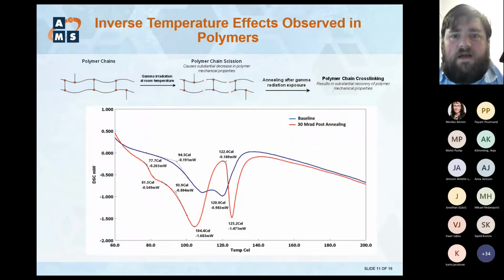Inverse temperature effects wise, because we are doing sequential radiation, then thermal, and we are doing radiation at lower temperatures, we did have significant inverse temperature effects in a lot of our samples under the current program we have. Basically, that process is you have a lot of gamma ray radiation at the lower temperatures, which induces a lot of chain scissioning and free radical formation.